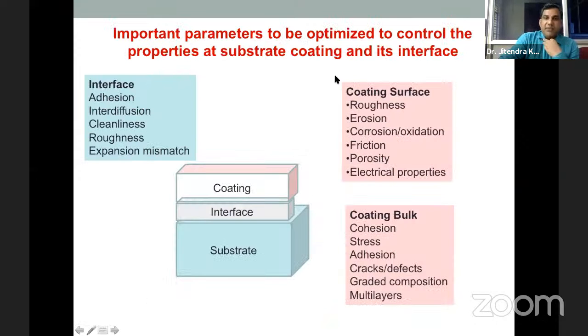So important parameters to optimize to control the properties of substrate, coating, and interface. These are the few things. Whatever the things, like in coating, if you want to go in bulk: what is the cohesive strength, stresses generated, adhesion, defects, or multi-layers; coating surfaces: what is the roughness, erosion rate, friction, porosity, or corrosion.